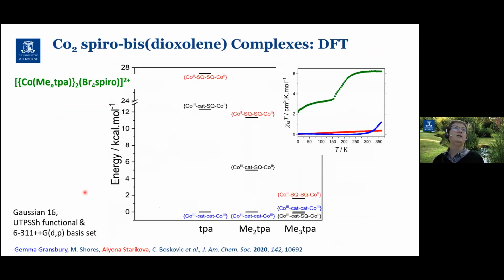So again, Aliona's DFT calculations really came into play here and really beautifully helped us to understand what was going on in this system. So she calculated the different analogs with the bromo Spiro. Here we have the plain TPA case. You can see the cobalt-3 catechol at both halves of the dimer is clearly the lowest in energy, and the other electromeric form is very high up in energy, and we're basically just stuck in the cobalt-3 catechol at both halves, which corresponds to the red data points in the susceptibility there.